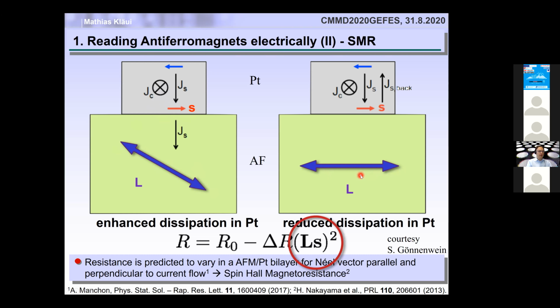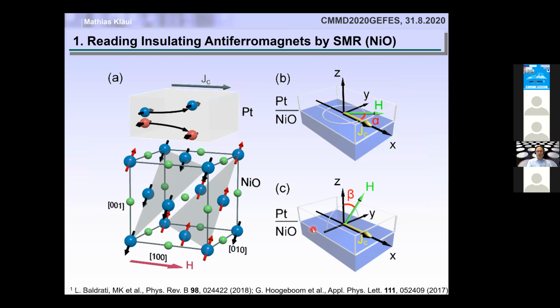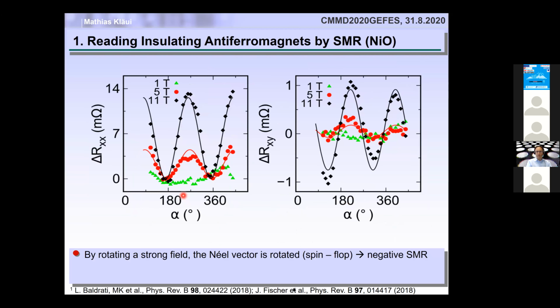And this was actually then done. What you expect to measure is the square of the dot product between the Néel vector and the spin accumulation. And we did this in nickel oxide, where we orient the sublattices in different directions and then measure the resistance of a platinum layer that is on top. So this was first done in the group of Bart van Wees in this paper here, and then later by us as well as the group of Sebastian Gönnenwein.